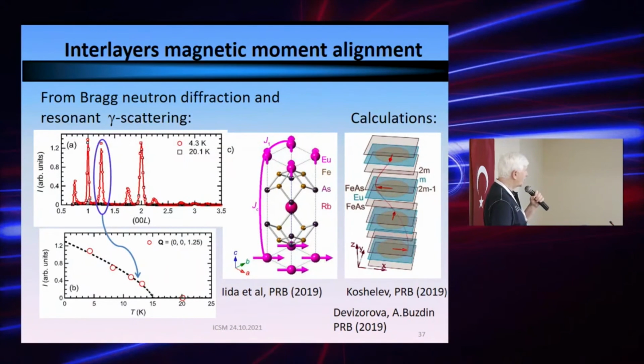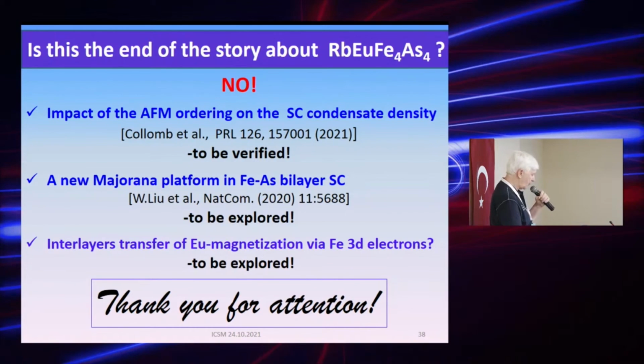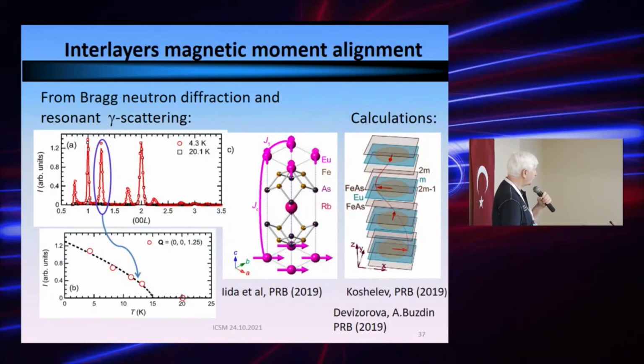If we think about the mechanism that might be responsible for torquing the europium layers relative to each other, certainly the europium planes, which are located far away from each other, somehow should interact. And it's not evident how it happens because the distance is too large. It's 1.3 nanometers for direct exchange to happen. Therefore, it is suggested that the interaction between the europium planes occurs via itinerant electrons.